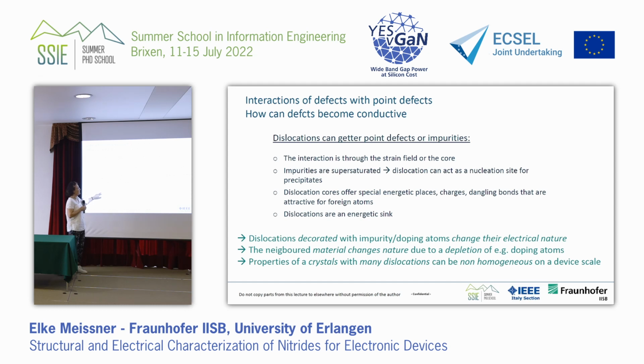So this is what can happen with dislocations. They grab the point defects or impurities, and get decorated. They can also grab dopants inside their strain field, not only at the core of the dislocations, but also in the strain field. And then something else happens. Not only do the atoms go to the dislocation and to the strain field, but the vicinity, the neighborhood, gets depleted. So if you want to have your dopant evenly distributed, what you create is dots of accumulated dislocations and depleted neighborhood. This is not what you want for a device where you like even properties all over the wafer.